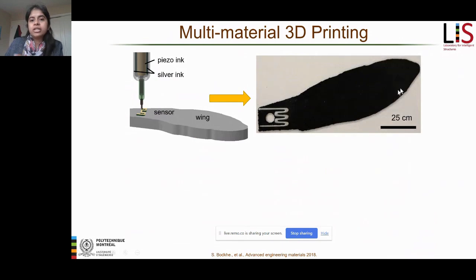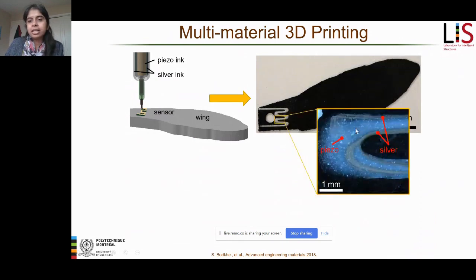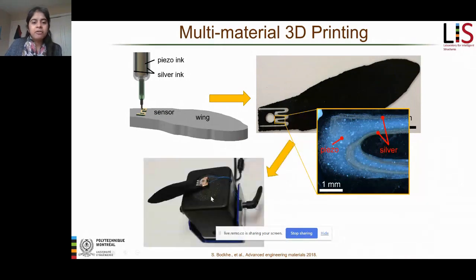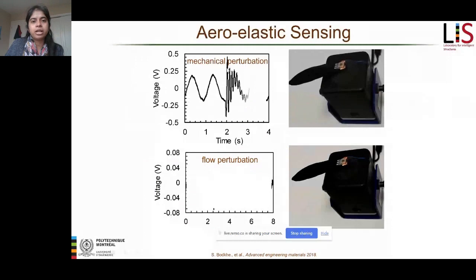And you can see here the picture, and this is the piezoelectric material and the silver electrodes. As you can see, the two electrodes do not touch each other, which is what we really wanted, so that there's not a short circuit. Then we mounted it on an electromagnetic shaker to see if our sensor works. And of course, it does work. So you can see here, when we hit it with a pin, it can detect the mechanical perturbation.